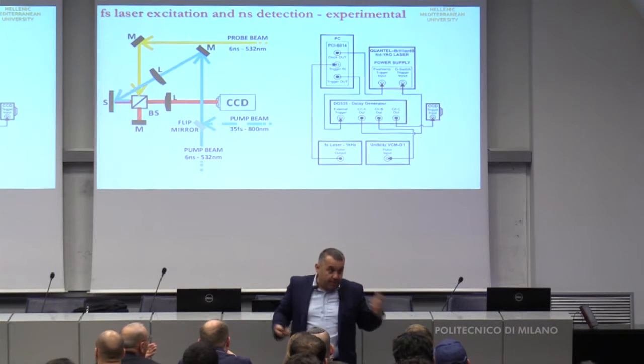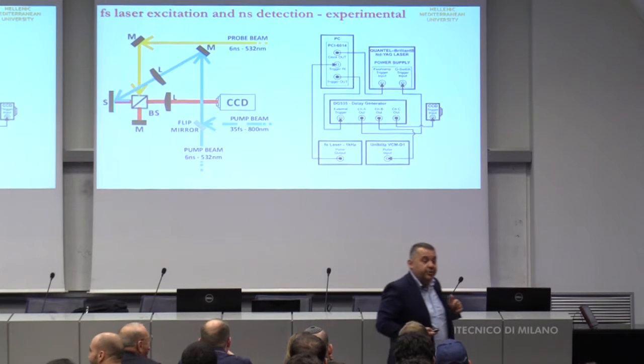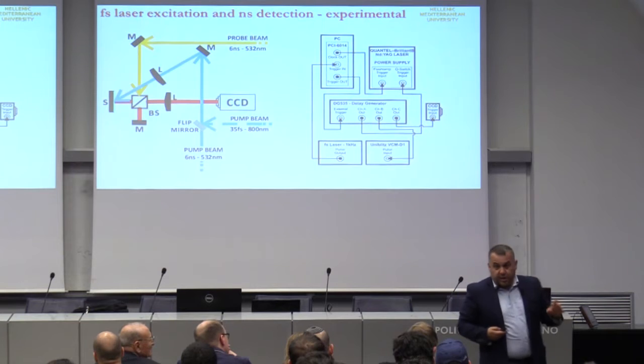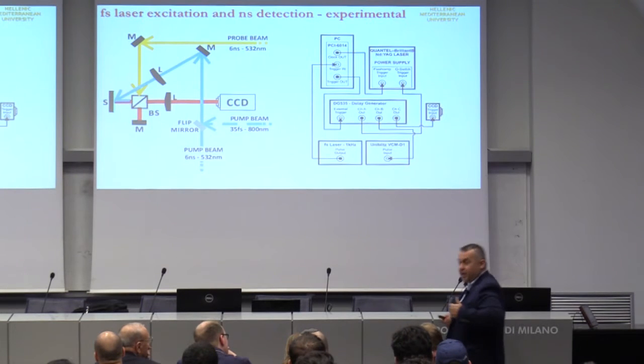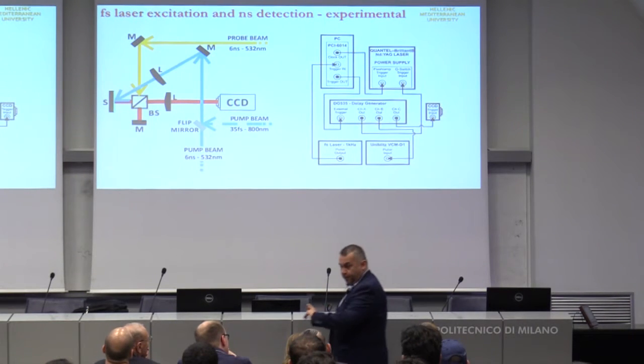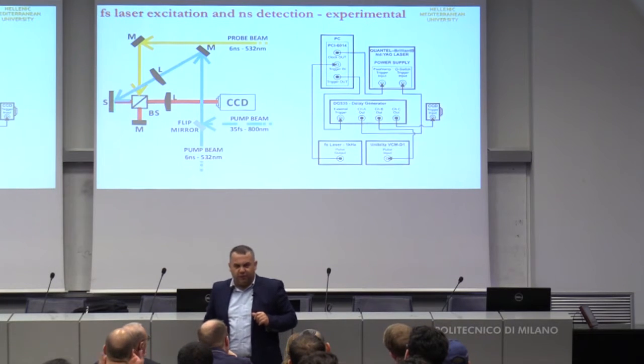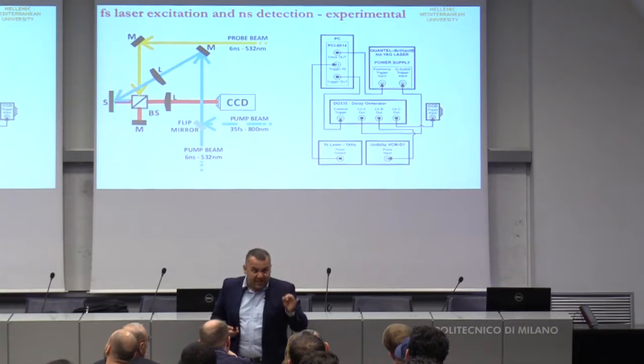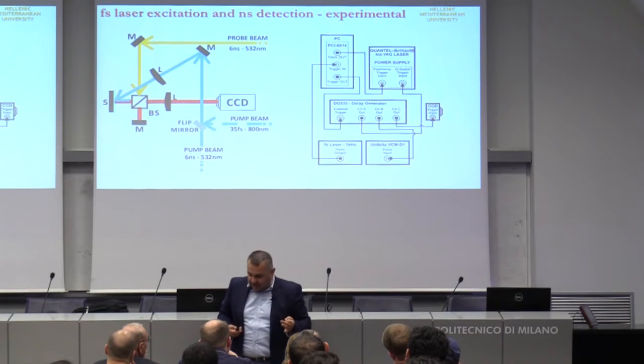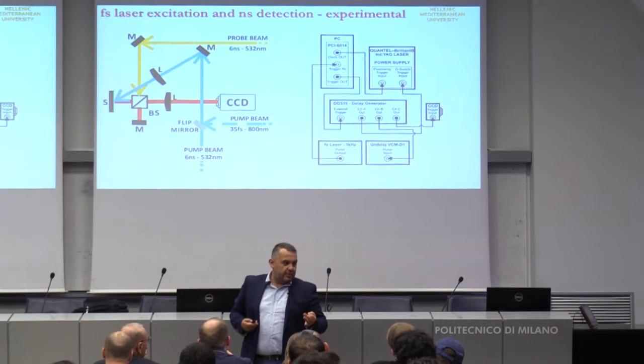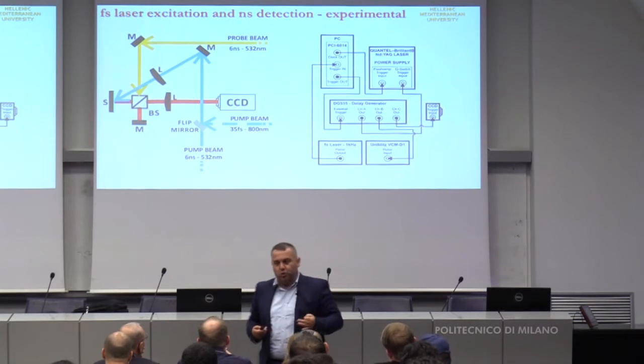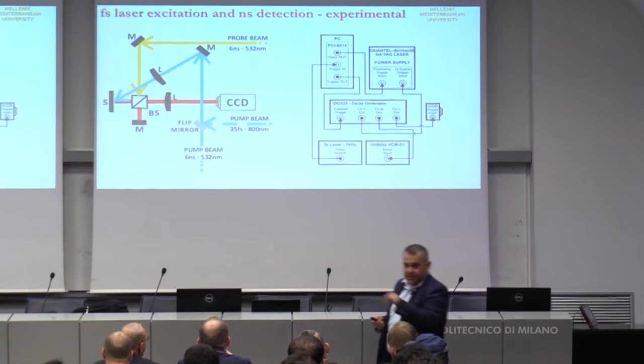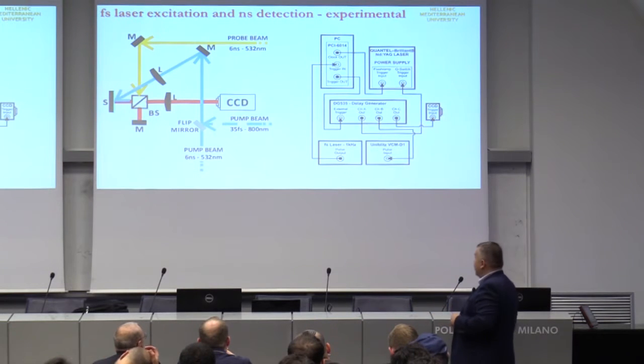Okay? But why femtosecond excitation? Femtosecond excitation, we believed, and now we have the first proof, is a completely different kind of excitation of this kind of Rayleigh waves. It's very much dependent on how fast you create this kind of waves, how fast you do that. And we have some first results published 2 weeks ago.